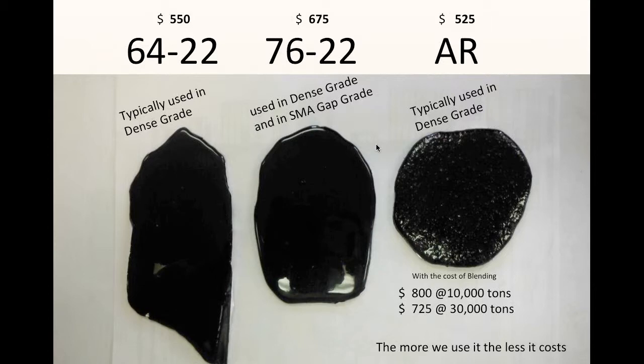Here's the same picture looking at the viscosity of the liquids, and here I've thrown together the cost, as I was mentioning, cost of a liquid ton. Standard asphalt, say $550, polymer modified 7622 at $675, and the asphalt rubber coming in at 25 bucks cheaper than the standard. Now, that's without blending costs. As you can see here on the bottom, 800 bucks a liquid ton. If you're blending 10,000 tons, it drops down to 725 bucks at 30,000 tons.